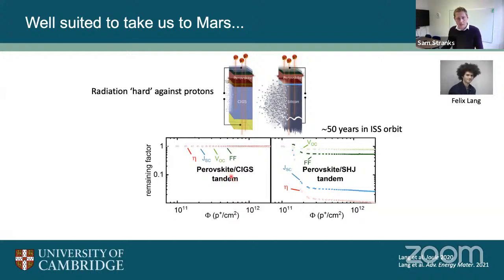And when we look at these tandems, this is a particular type of perovskite tandem cell, you can see it's very, very stable and it doesn't degrade after a very high dose of protons. Whereas if we look at something that has silicon in it, this perovskite-silicon cell, that degrades very quickly. We see losses in the performance parameters of these cells. That's because silicon, when you produce defects, that really does kill the cell performance. Again, that's why you have to produce them at very high temperature. So this shows that these perovskite cells are very, very promising for space applications, and particularly for very long-lived cells in space.